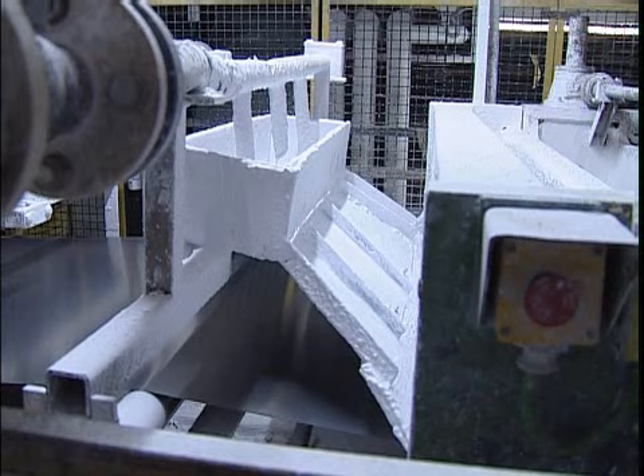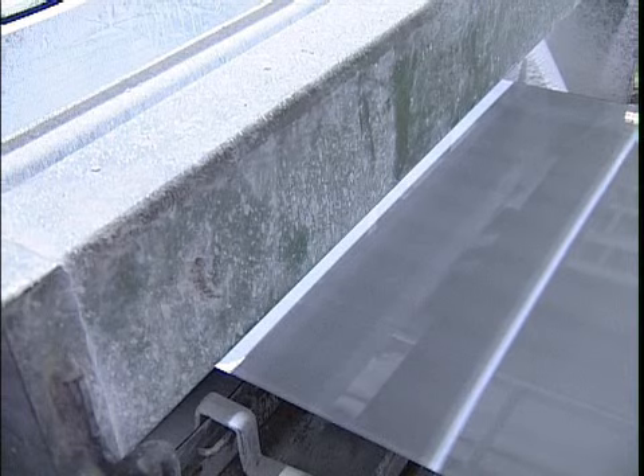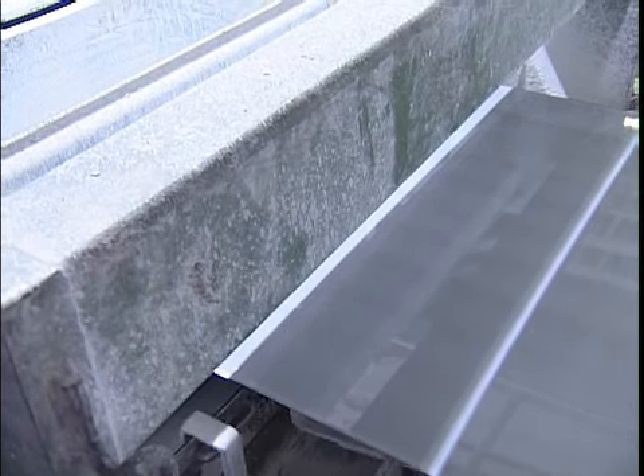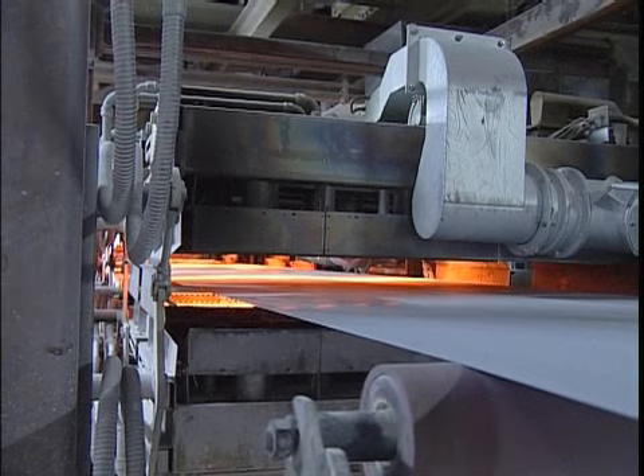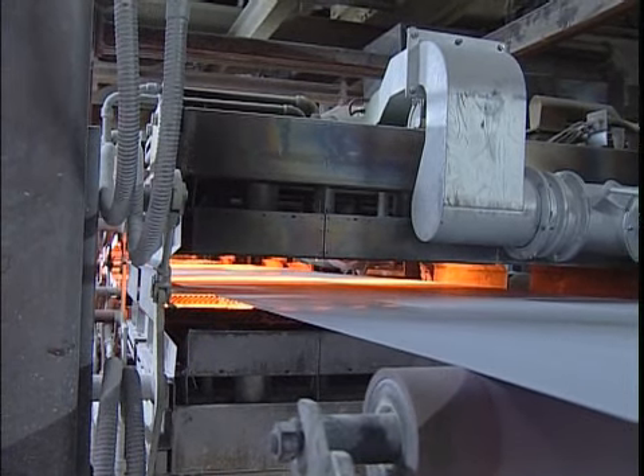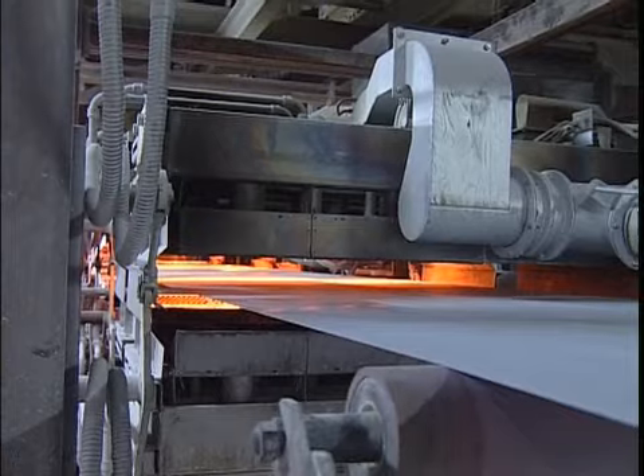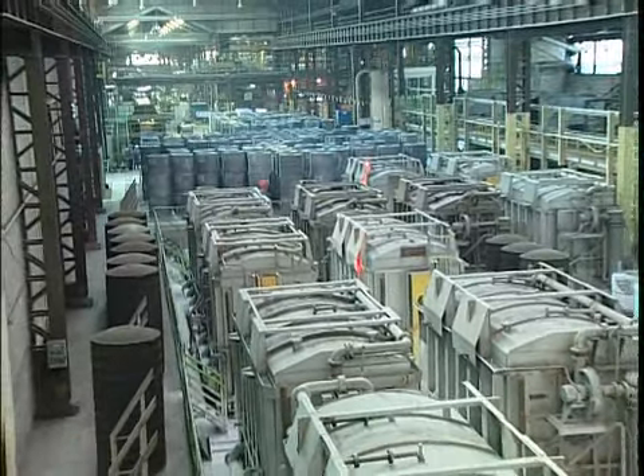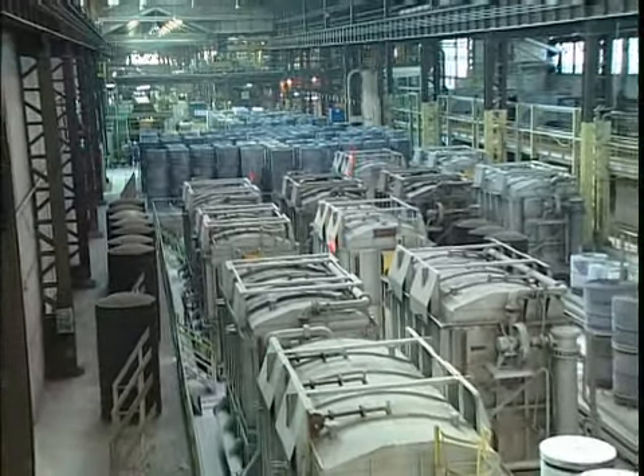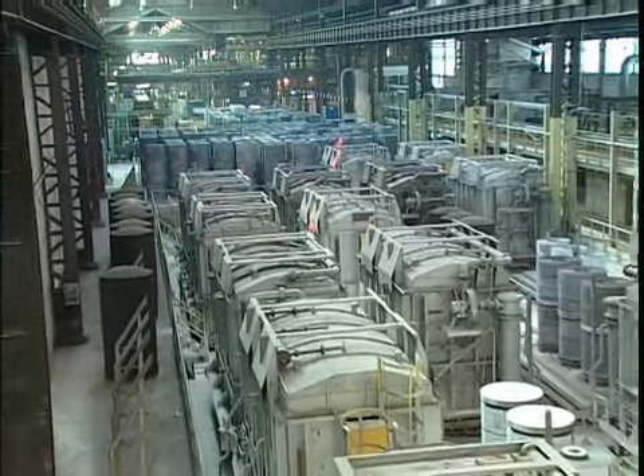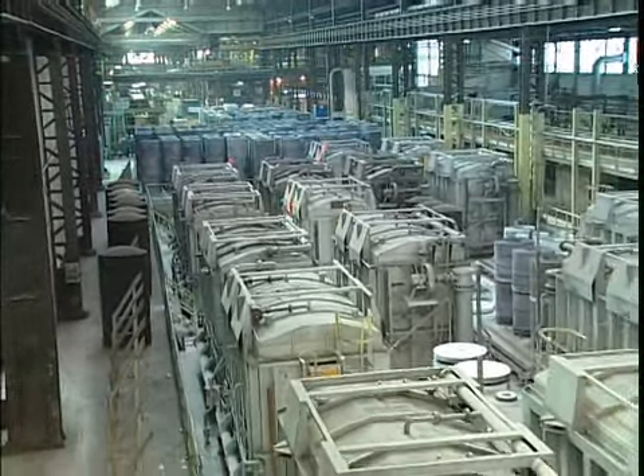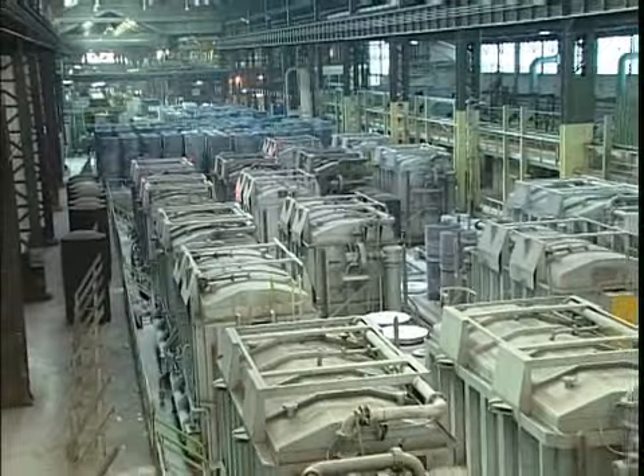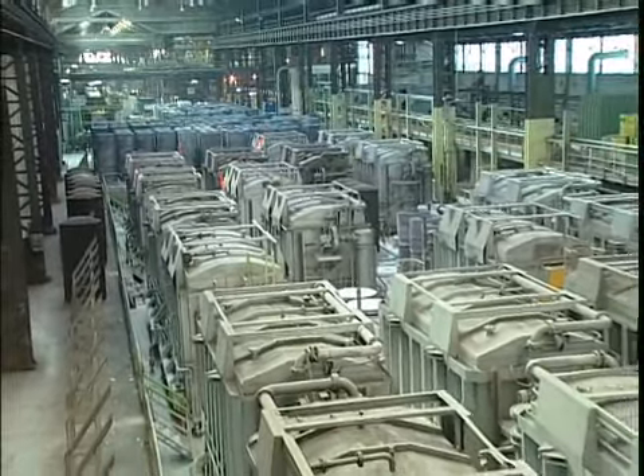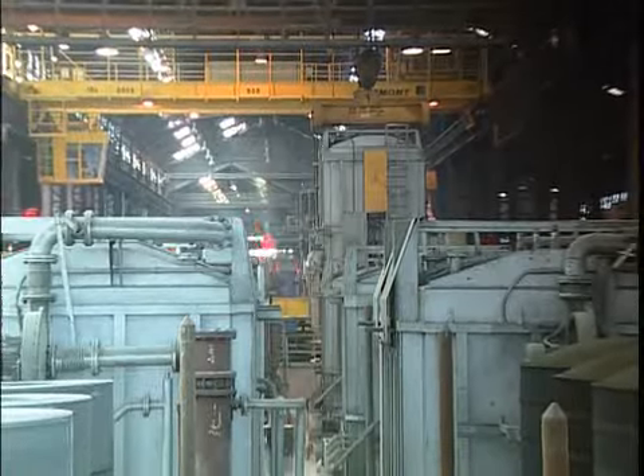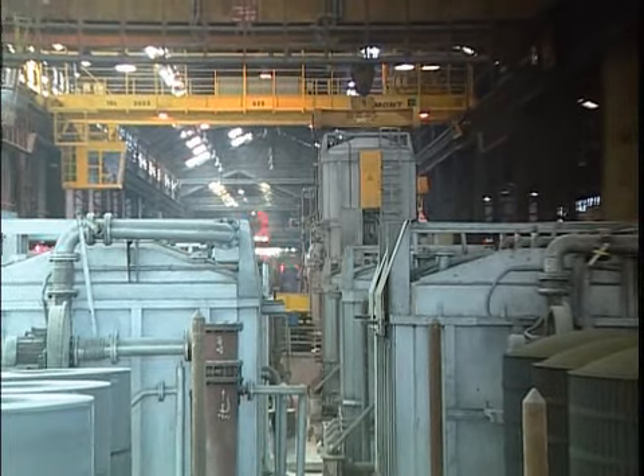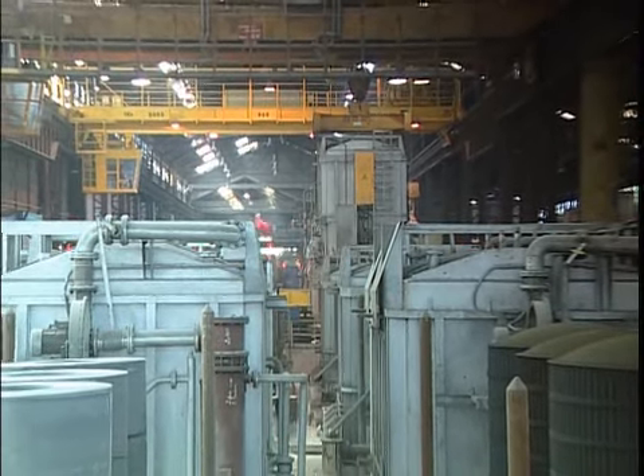At the end of decarburization and the annealing, an emulsion of magnesium oxide is applied to both sides of the strip and dried. During the high-temperature box annealing, the second step of grain growth, a so-called secondary recrystallization, takes place at a temperature of 950 to up to 1200 degrees centigrade and forms the unique Goss texture named after its discoverer.